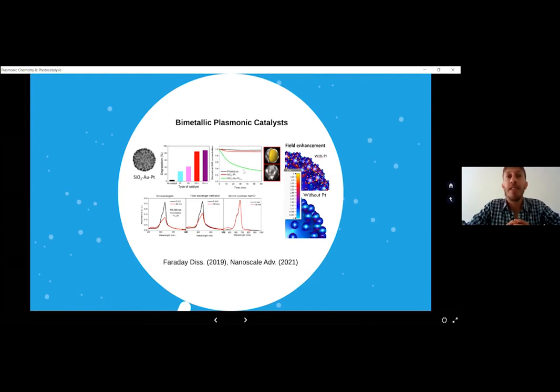So rapidly in this field, the idea of combining materials started. What happens if we have a plasmonic material that can harvest the light and excite the plasmon modes, and we also have another material which is good at catalyzing a given reaction? In here, for example, Jorge from King's explored the idea of having big silica-supported nanoparticles, and on top of that, small gold nanoparticles decorated with platinum clusters.